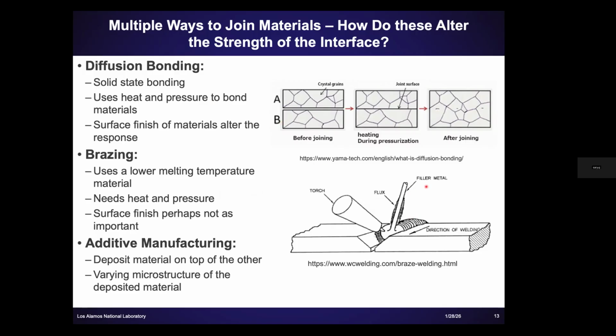But you can also have things like, as shown in this image, braze welding. Again, the concept is the same, but here you're just directly melting that braze and not really applying any pressure or temperature, more similar to welding. And then, of course, you can have additive manufacturing where you have a base material and you can deposit any other material on top of it. You can use electron beam additive manufacturing. You can use laser powder bed fusion, whatever is available. But the point here was, if I take the same two materials and I change the morphology of the interface between those two materials by changing how I bonded them, would that affect the dynamic behavior?